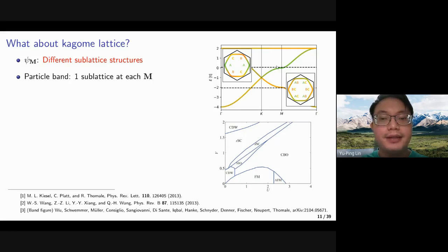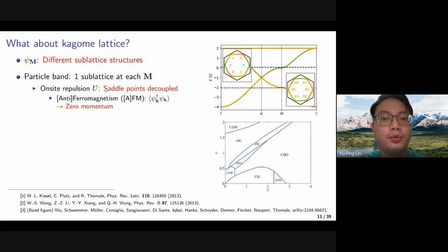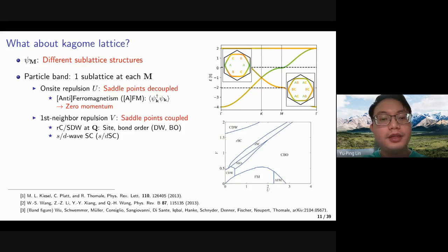First, let us look at the upper band, where there is only one sublattice site contribution at each saddle point. If we introduce the on-site repulsion, where A is only coupled to A, B is only coupled to B, and C is only coupled to C, we'll see that the saddle points are not coupled to one another. And with the on-site repulsion, the leading instability at low temperature will be either ferro or anti-ferromagnetism, which is on the same site at the same saddle point, and it will be a zero momentum instability. However, if we introduce the first neighbor repulsion V, the saddle points could be coupled because now we're having interactions between A and B sublattice sites, B and C sublattice sites, and C and A sublattice sites. So we could now couple the saddle points, and we would have similar results to the graphene and triangular lattice.